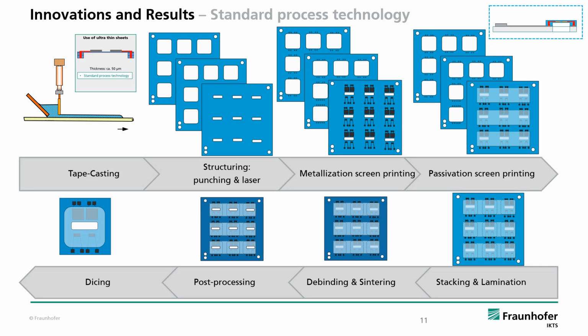In the scheme, you can see the standard technology explained for the mass flow sensor with ultra-thin sheets. First step is tape casting a slurry, which is a mix of glass ceramic and organic binder, onto a carrier sheet. After drying, it is a flexible green sheet. It is cut in different sizes. Normally, we prefer 4 by 4 inch. These tapes are then structured by punching and laser processes.